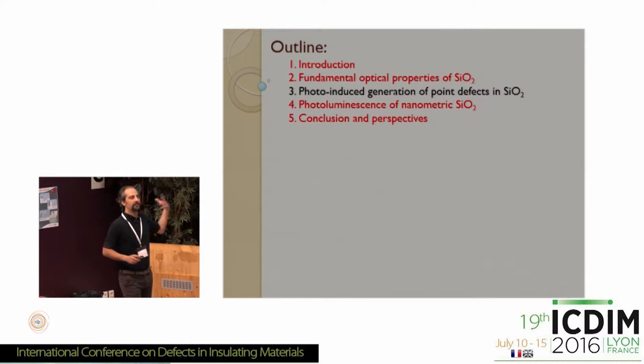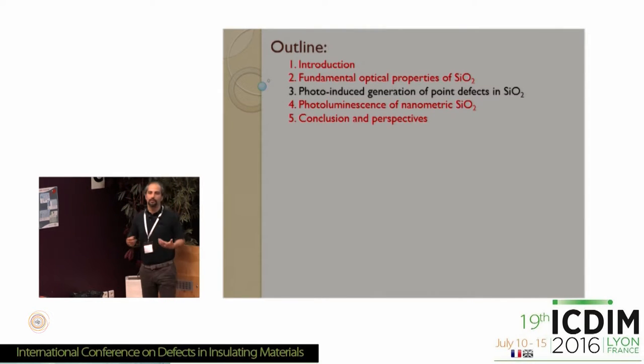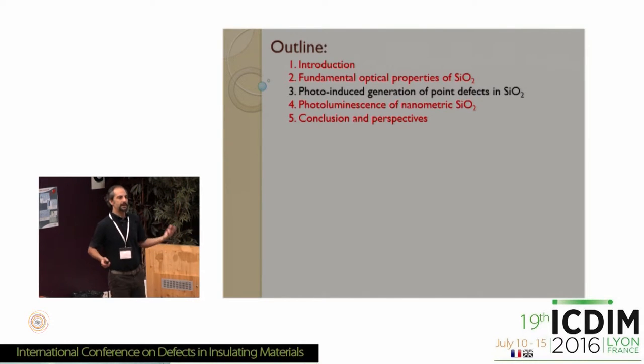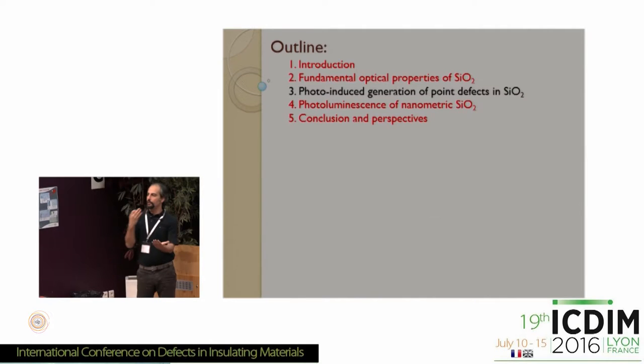In fact, most of the studies used what I would describe as an ex situ method to study these processes. By ex situ method, I mean you take the sample, you irradiate the sample, you wait some time, and then you use several spectroscopies to see what the effect of irradiation has been on the sample. This, of course, is very informative, but there is the possibility that when you do this, you are missing something because you don't monitor the kinetics of all this.